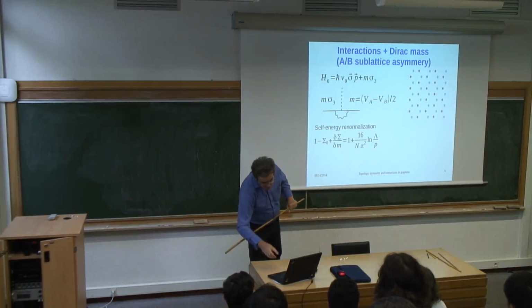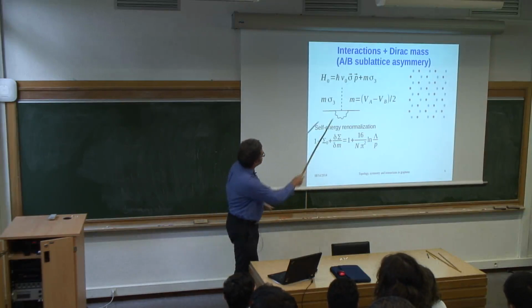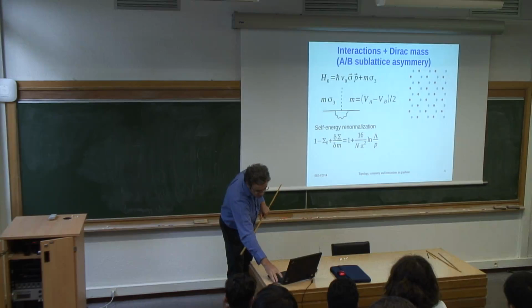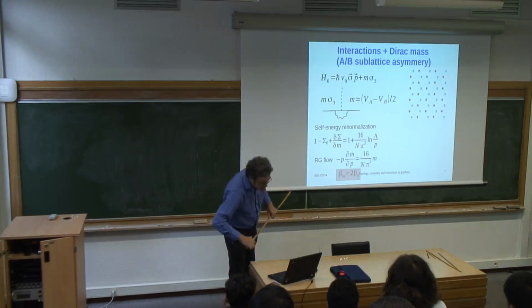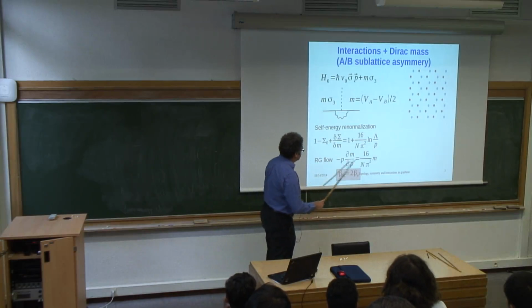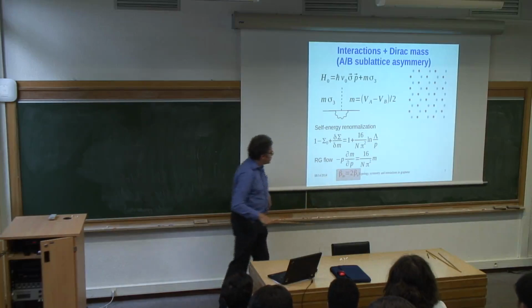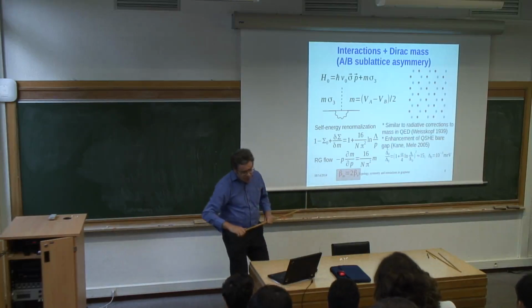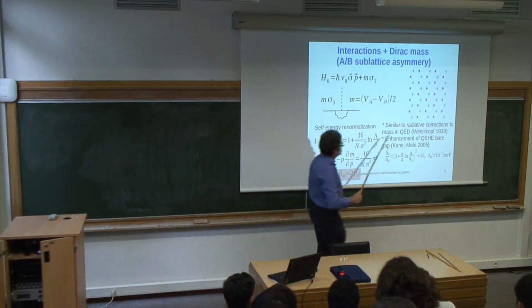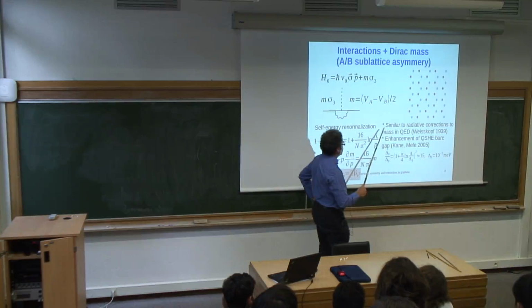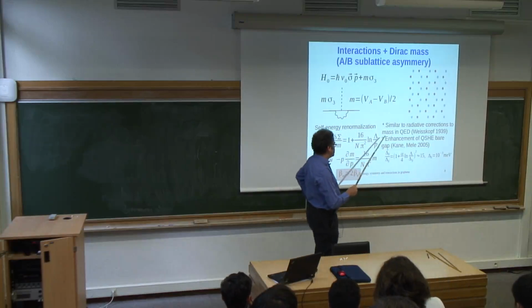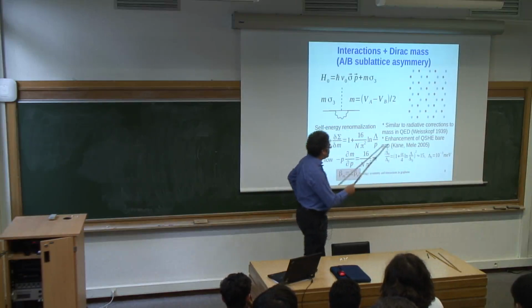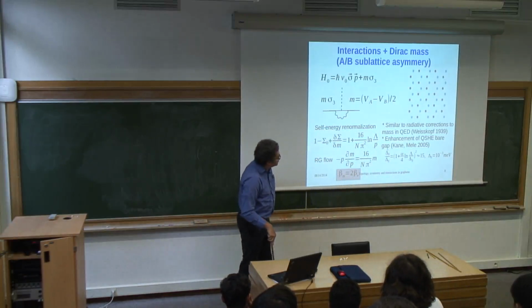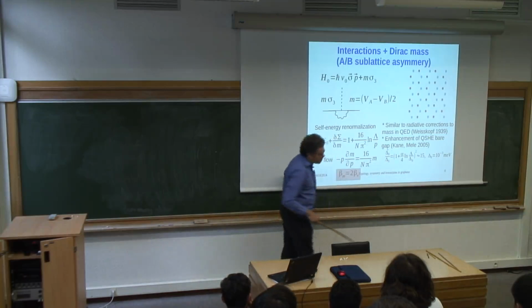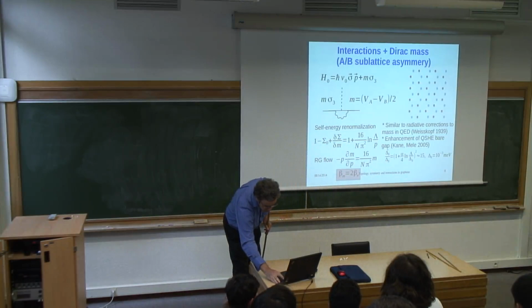and can treat this log together with various other logs that we found, and show that the RG equation for mass generates this exponent, which is related to the velocity exponent that we derived yesterday, and it's similar to how radiative corrections in real QED have been treated by Weisskopf, and also how QSHE gap enhancement has been discussed in the Kane and Mele paper.